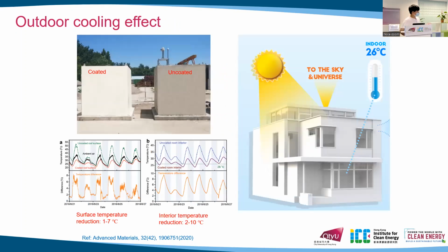Then we applied our radiative cooling coating onto a real-world model room. After we applied the coating, the surface temperature of the model room can be reduced 1 to 7 Celsius lower than ambient air, and the interior temperature is even lower. It can reach 2 to 10 Celsius lower than ambient temperature. While for the uncoated one, we can see that both surface temperature and the interior temperature are higher than the ambient. So our coating can achieve real subambient cooling in a real-world building.